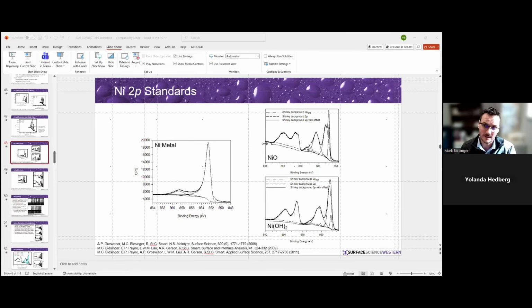Sometimes for something like nickel sulfide, you may have to break these samples, like a fracture sample, so that you have a pristine surface. If you have an attached glove box on your system, or we used to do a lot of work where we actually broke materials in situ in the vacuum of a system so that we could look at pristine surfaces. If you have access to a gas cluster ion source, that's a great way to look at surfaces without reducing that surface, as opposed to a monoatomic argon ion beam.